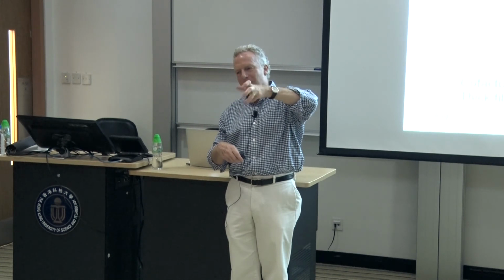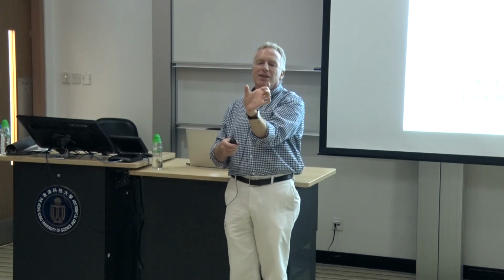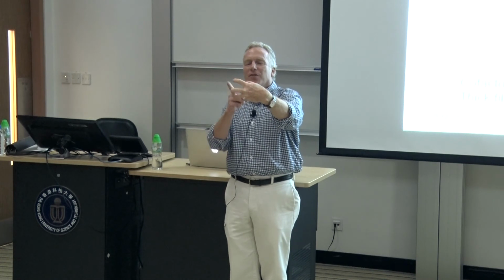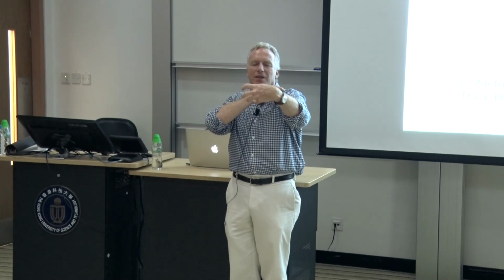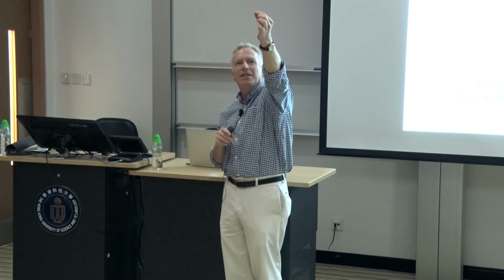Under stress, we've looked at what happens if you turn on and off the cofactor conditions. We're thinking of a polycrystal, and so an arbitrarily oriented grain, and we look at the strain in the direction of the stress for an arbitrarily oriented grain. Another way to think of it is, instead of an arbitrarily oriented grain, fix the orientation of the grain and let the tensile axis move around. Then you can think of just a vector, and there are certain directions in which the crystal cannot deform very much. If you did a polar plot in 3 dimensions of the strain in direction E, and you plot the length of the vector as direction E, you get a kind of bumpy sphere.